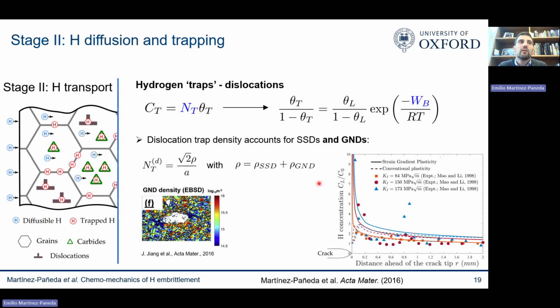And this is an important bit: GNDs dominate behavior near inclusions, cracks, and other stress concentrators. GNDs are also obstacles to other dislocations, so they bring local hardening, as you can capture through strain gradient plasticity theories. When you do that, it's the only way you can actually capture the very high hydrogen concentrations ahead of cracks and other stress concentrators, like you see here in the experiments. So GNDs and strain gradients are important.